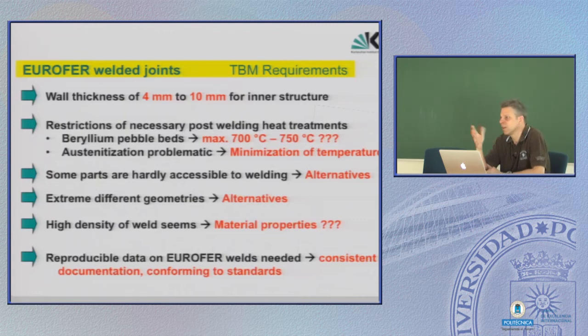I haven't mentioned it yet, but you know it since it's obvious. If you melt Eurofer and cool it down, then it produces martensite and is hard and brittle. So after welding it's the same as after quenching. You have to perform a heat treatment. Then you could think of two types of heat treatments. One was pushing the reset button, as I said yesterday, repeating a full heat treatment: austenitization or solution annealing, quenching and tempering. And with that you should have completely restored material and all the weld effects should be away.